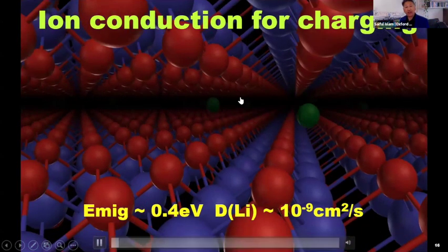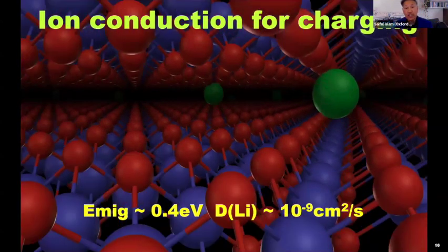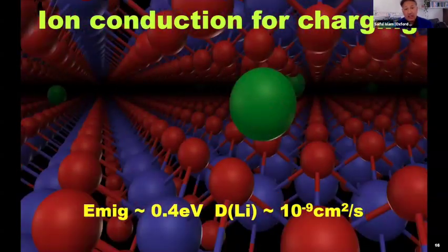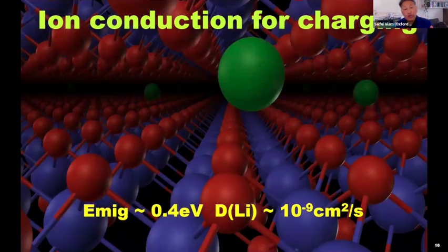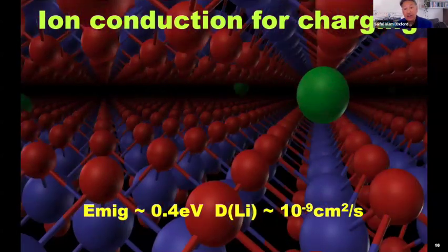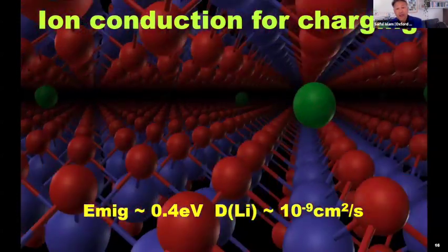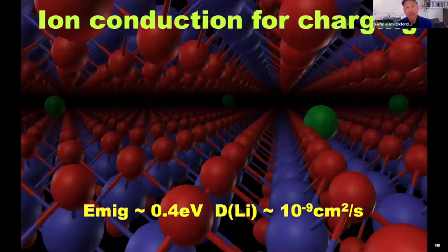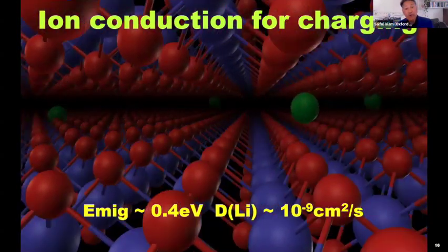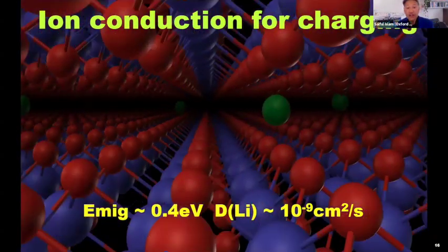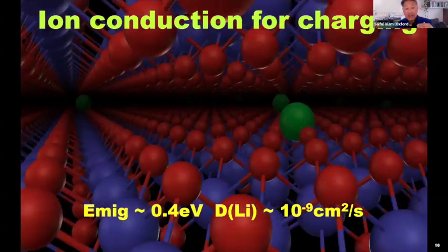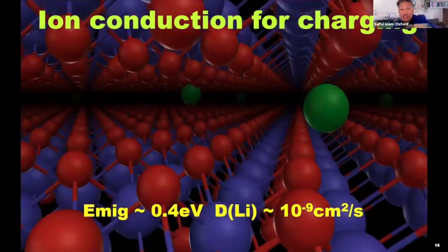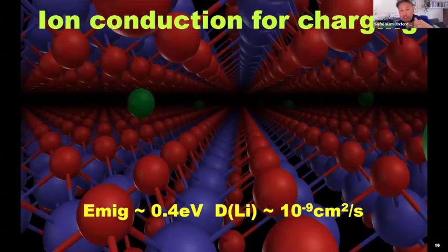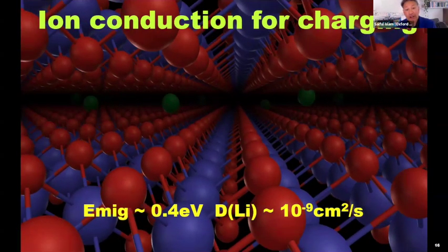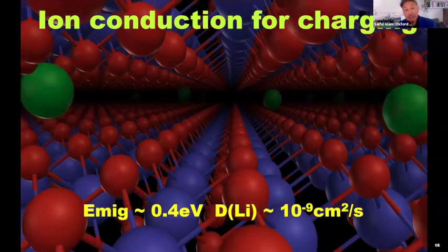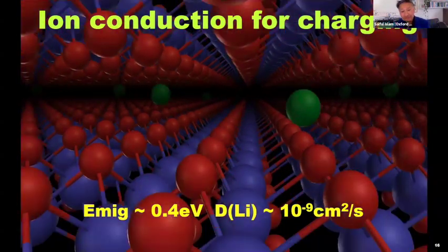This is a layered oxide, a layered positive electrode, lithium cobalt oxide. The blues are cobalt, the reds are oxygen, and the lithium ions are in green. This shows you a molecular dynamics simulation showing the lithium ions moving through the 2D layers. You can see it's through the sheets of these structures, and that fast diffusion through those sheets is very important. So as in life, the important stuff is happening between the sheets.